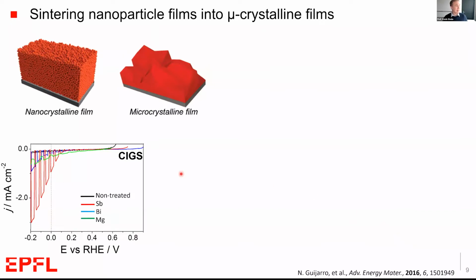And to illustrate that, again, I show some of these JV curves, or linear scanning voltammetry curves, where we change the potential and measure the photocurrent. In this case, we're turning the light on and off, so you can see the dark current and the photocurrent here. We want to get the largest photocurrent possible. And you can see in the non-treated sample, the black curve exhibits essentially no photocurrent at all. But when we use these additives to help increase the crystallite size, we do see a big increase in the photocurrent.